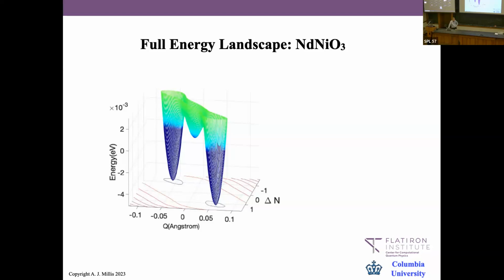Is it all sorts of things? I don't have a good answer to that, because the problem is after you go beyond about 0.15 in these units, or maybe 0.2, the lattice energy gets very strongly nonlinear and all kinds of weird things happen to the chemistry. So the way I would say it is that delta Q can't be much bigger than about 0.15 or 0.2,